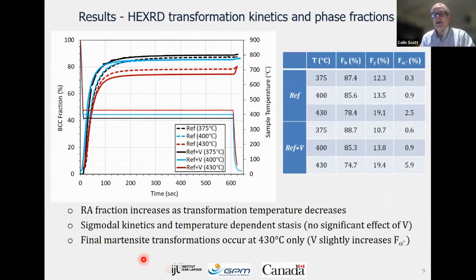Now, the high energy X-ray diffraction. So we've got these in situ experiments where we're heating up and then cooling down the specimen essentially in a dilatometer. And we can measure the variation in the austenite lattice parameter or the ferrite lattice, everything that you might want in the typical XRD experiment.